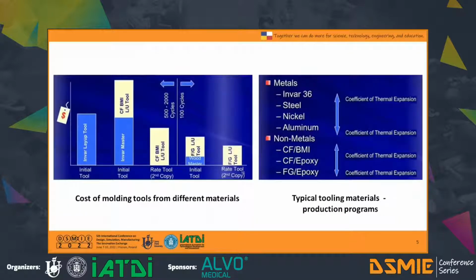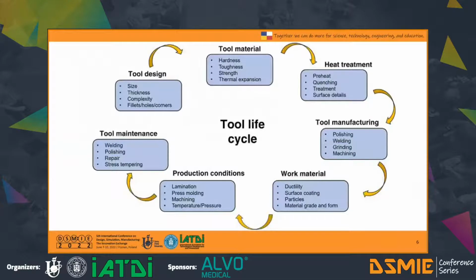The mechanism of lifetime reduction in the composite shaping surface of the tool is different from that in the metal one. In the course of repeated temperature load, stability of the physical and mechanical characteristics of the PKM is lost. However, despite serious developments in the area, the short lifetime of both metal and composite molding tools is recorded in production practice. This is because, in the search for more convenient, lightweight, and uniformly heated structures of molding tools, thin weld frame and composite solutions are usually developed, with the optimal parameters of each body based on critical ones.